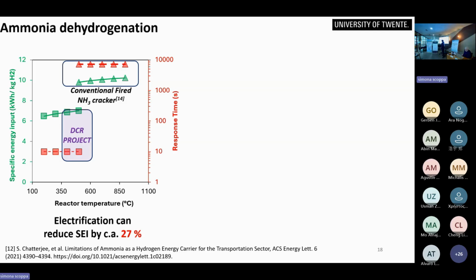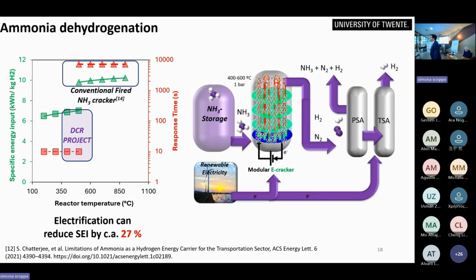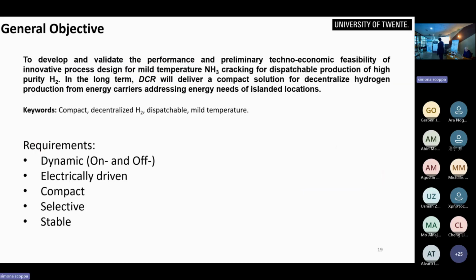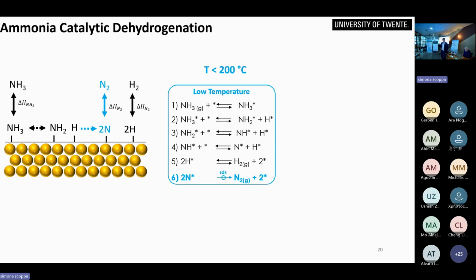And the beauty of it is that if you now couple this to electrical heating, you can now go from, let's say, dynamic operations that takes maybe hours to days to maybe seconds. And the general concept is that you now have a Joule-heated system where you are overcoming the endothermicity of the reaction by providing the heat with an electrical source, and then you couple that to whatever absorption or pressure swing absorption system you would like to use. But how exactly? So the general objective of this project was to do this sort of feasibility study of the proof of concept. With that, we wanted to have something that was dynamic on and off, electrically driven, compact, and selective, and that could be stable over time.